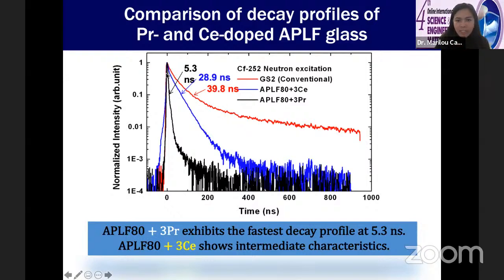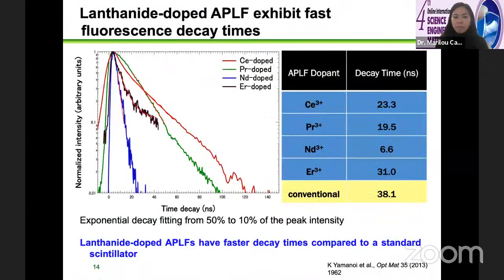We can see here that the response time for the praseodymium doped APLF, which is this black curve, is very fast. It's 5.3 nanoseconds. It's one of the fastest scintillators that has been reported. For the cerium doped scintillator, it has an intermediate decay time of 28.9 nanoseconds. So in terms of decay time, the praseodymium APLF scintillator is superior to the cerium doped one and the conventional scintillator. In fact, investigating the decay time using different rare earth ion activators as dopants, the decay times are still so much faster than the conventional scintillator.